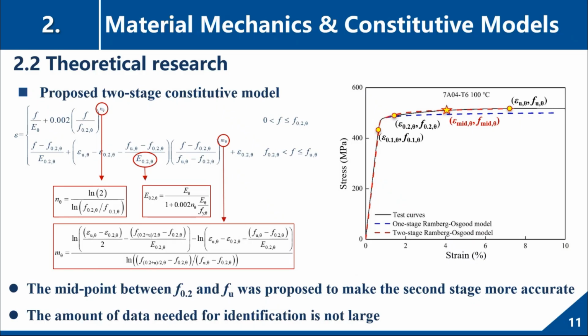And this one, because we can see that there is a very important point. It's called the middle point between the yield point and the peak point. Why we use this point to capture the second stage? Because for aluminum alloy, sometimes it will fracture before the strain equals to 1%.